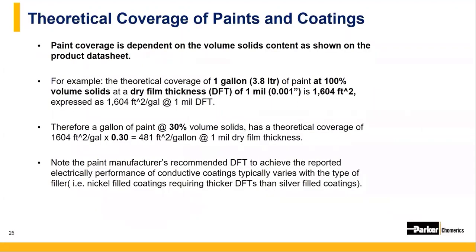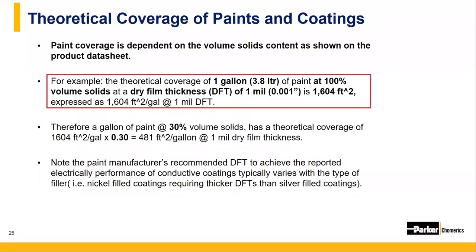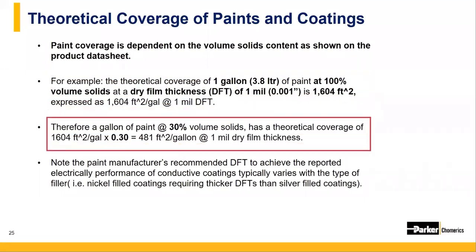To calculate the theoretical coverage and the cost of an electrically conductive coating or paint, you'll want to note the percent volume solids of the material the manufacturer notes on the technical data sheet. For example, the theoretical coverage of 1 gallon of paint at 100% volume solids at the manufacturer's recommended thickness, called dry film thickness, or DFT, of 1 mil is expressed as 1,604 feet squared at the DFT. So taking that formula, if I had a gallon of an electrically conductive coating with a 30% volume solids and a DFT of 1 mil, then the theoretical coverage of that gallon of material is 481 square feet.